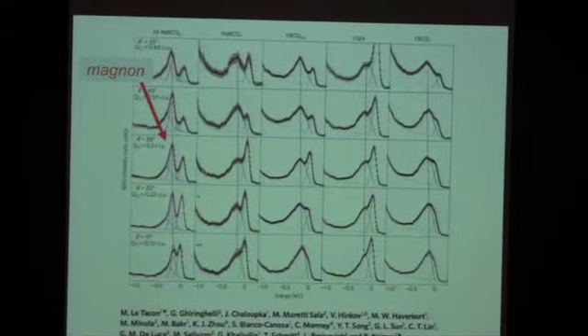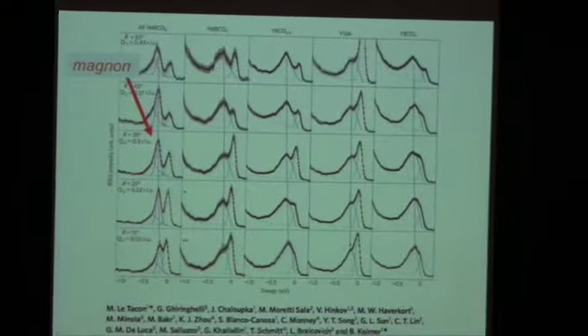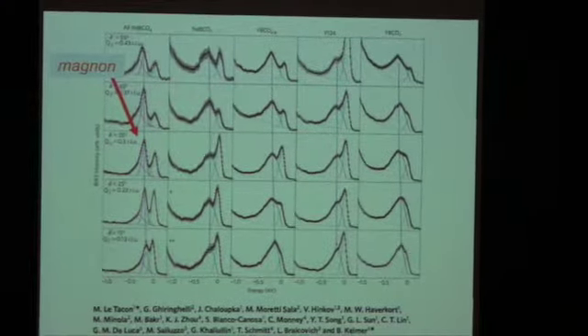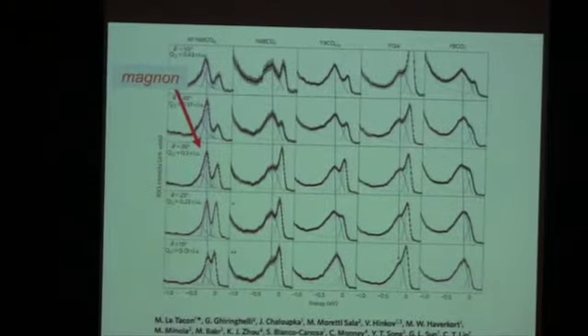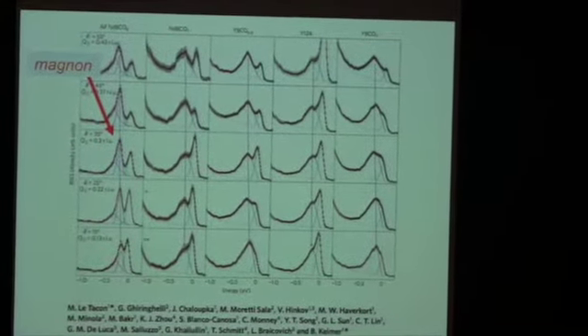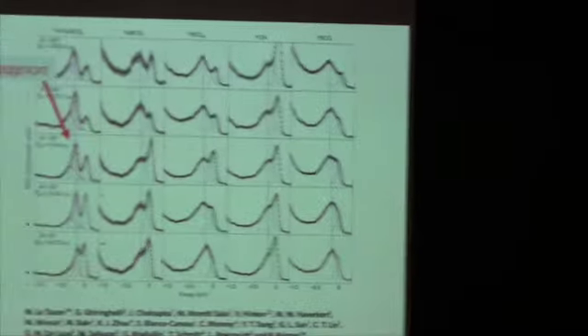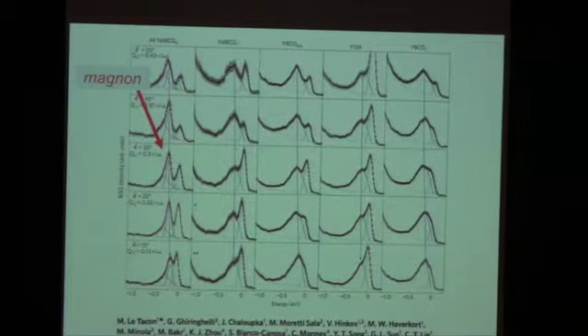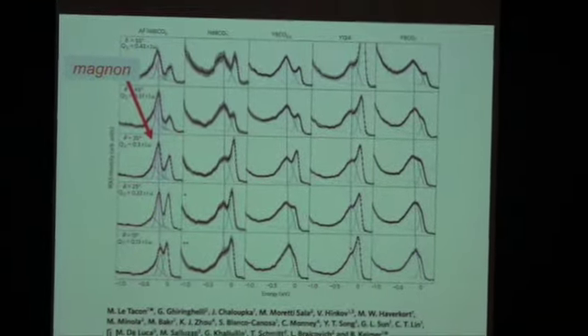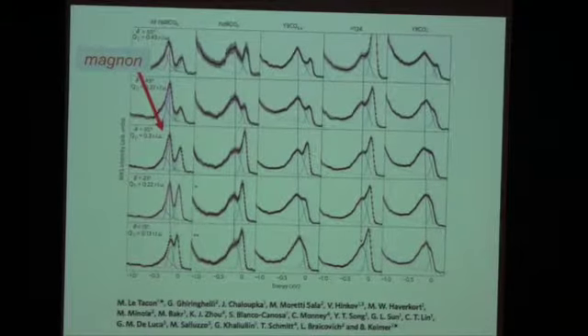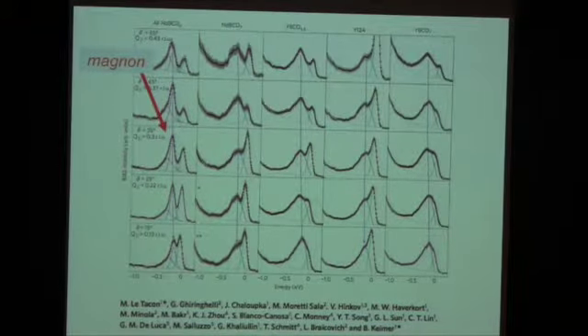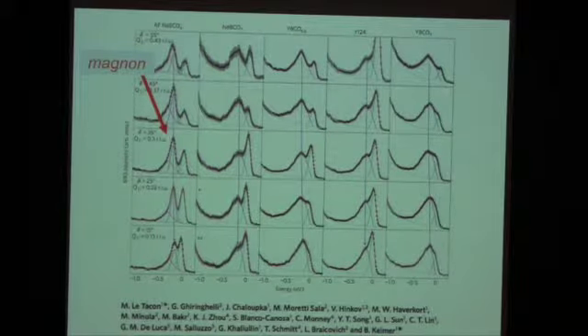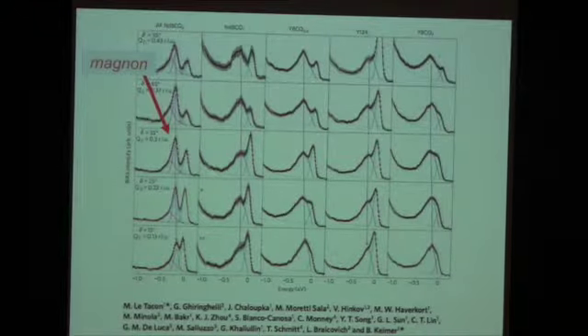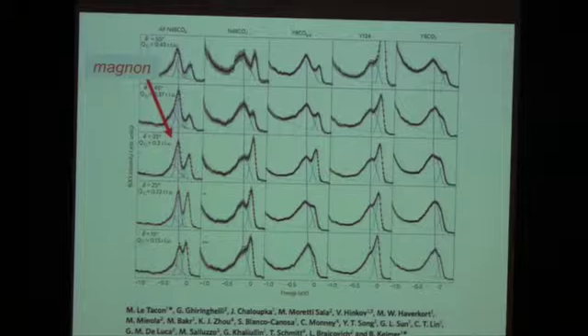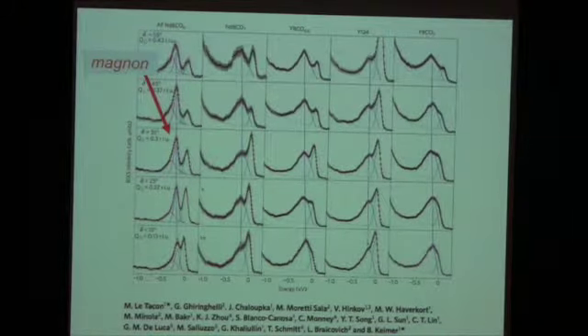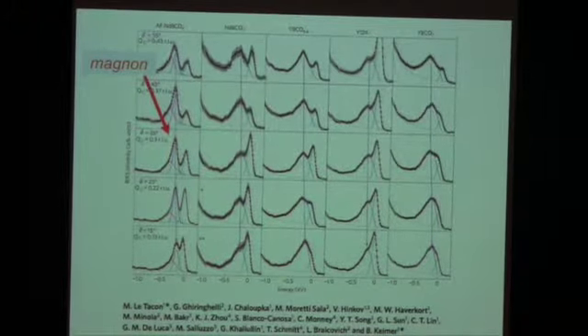So the conclusion is that if you look at the magnon dispersion for the undoped system, and now you go to a doped system, you actually find back excitations that have a dispersion that looks exactly like those magnon excitations, but they're broadened somewhat. And we also know now for some systems, for the electron-doped systems, they are hardened, so the energy of those excitations is a bit higher than for the undoped system. For other systems, it's a bit lower, but they remain.